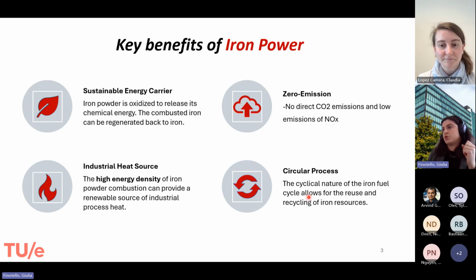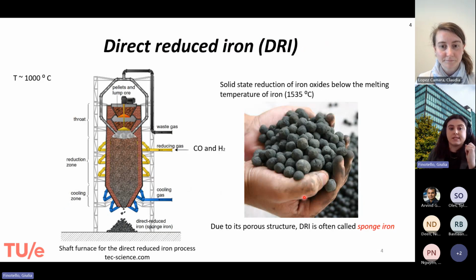So let's get more into the reduction processes that are available. We know already from the steel making industry direct reduced iron. This is already done in a shaft furnace, where we have a solid state reduction of the iron oxide. In these very large facilities, pellets and lump ore are introduced, and the reducing agent can be hydrogen or a hydrocarbon mixture with CO and hydrogen. Temperatures are relatively high, and what we produce here is direct reduced iron, or sponge iron,